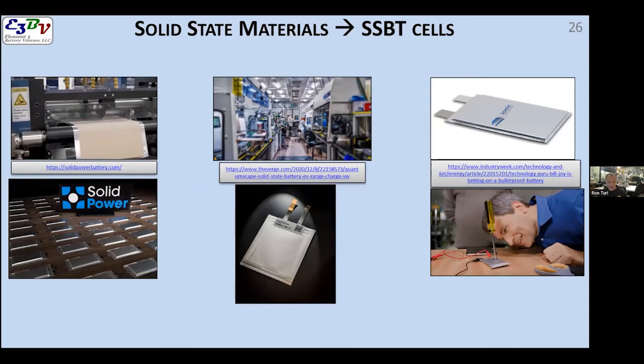You can have a silicon anode that has no liquid electrolyte, it has a solid state electrolyte, and technically that would be a solid state anode as well. However, by and large, solid state materials tend to be anodes where you're plating lithium. Here's an exception right away. Solid Power actually has material that is silicon-based material in the anode, but other companies like QuantumScape, they have something they call a no anode because they plate directly onto foil.